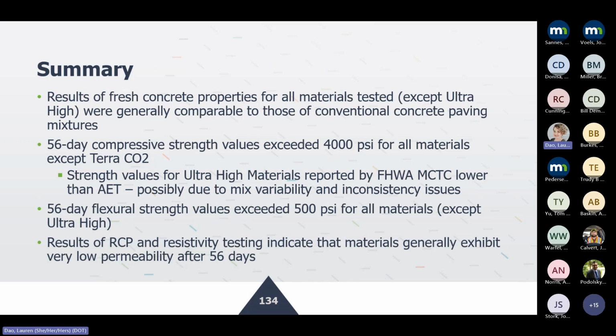And then no issues with the 56-day strength values for most of the materials. They exceeded 500 PSI, well within the requirement that MnDOT has. And as you saw on the previous slides, the RCP testing and the resistivity testing did show that these materials have very, very low permeability after 56 days.